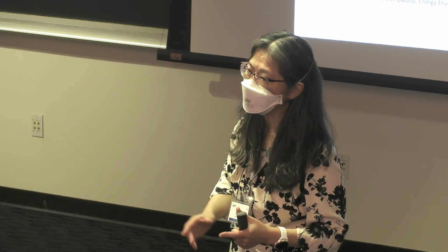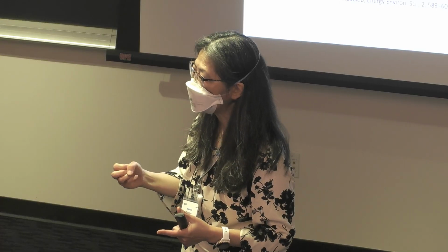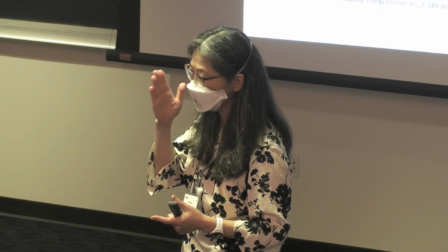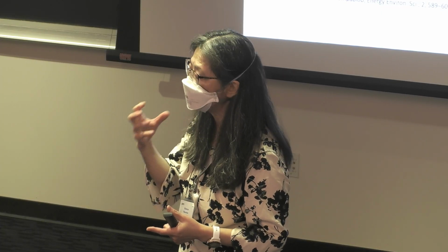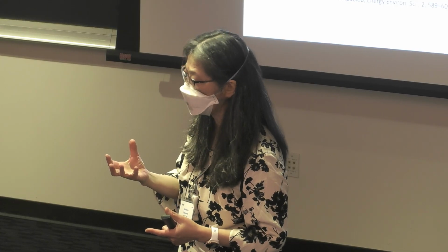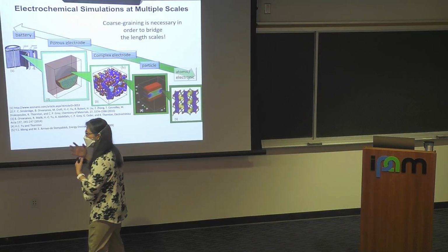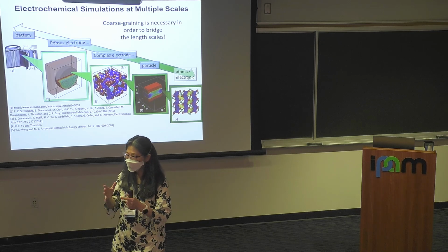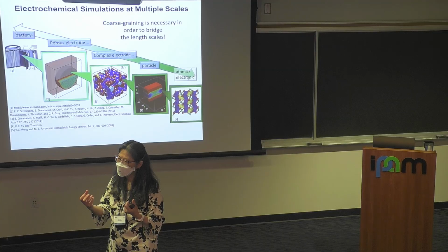That was one of the reasons this material system wasn't considered. By nanosizing, you make it harder to create interface, and also introduce a large pre-existing interface, which is the surface of a particle. So that allows us to eliminate the hysteresis from that. And because the interface is already there, it's phase separating, but it's not costing too much energy.